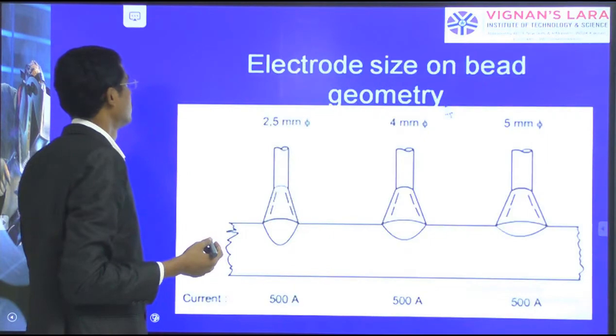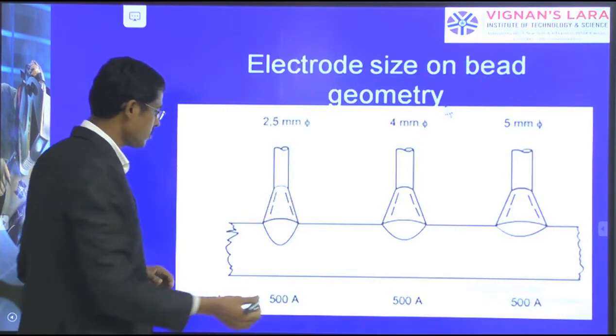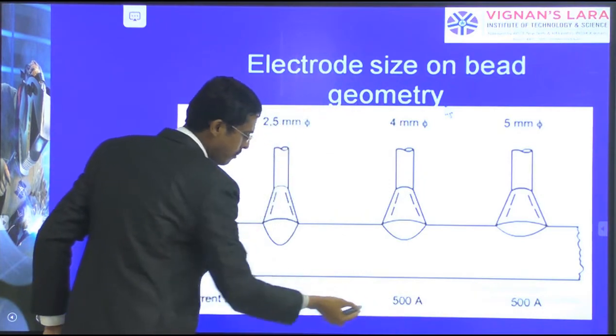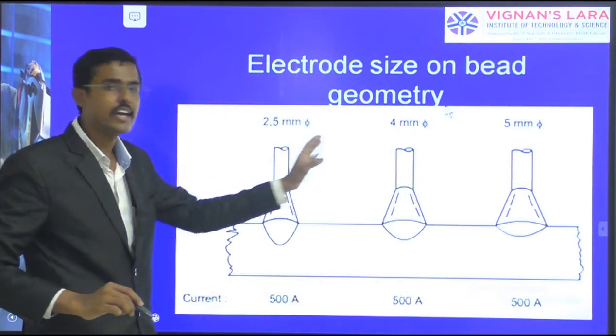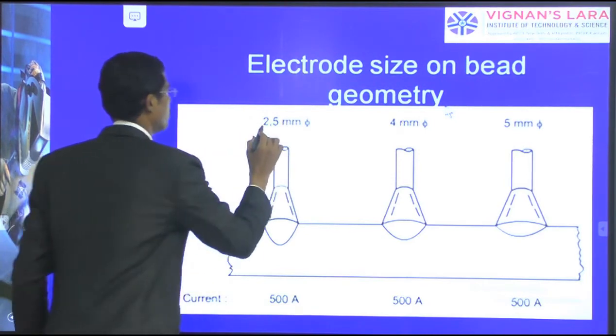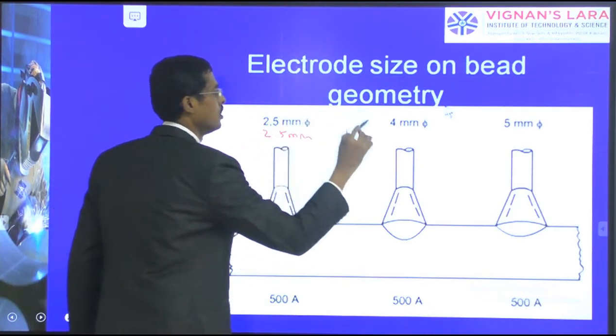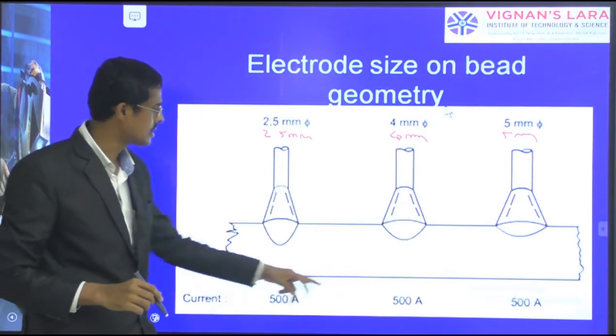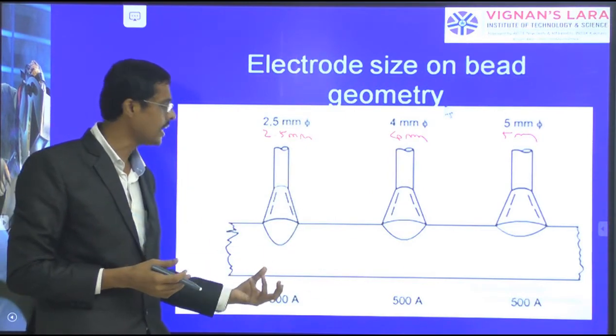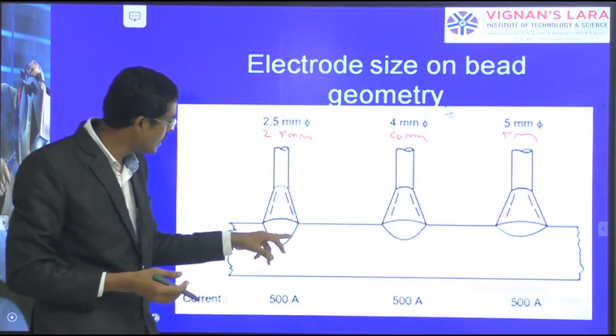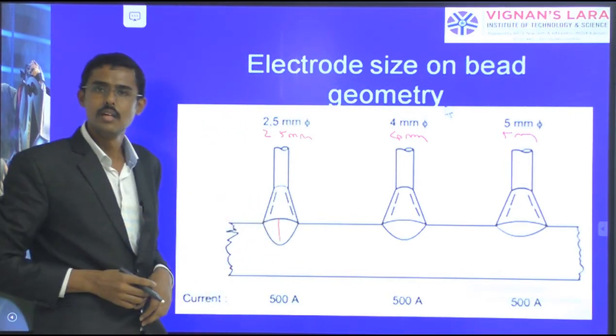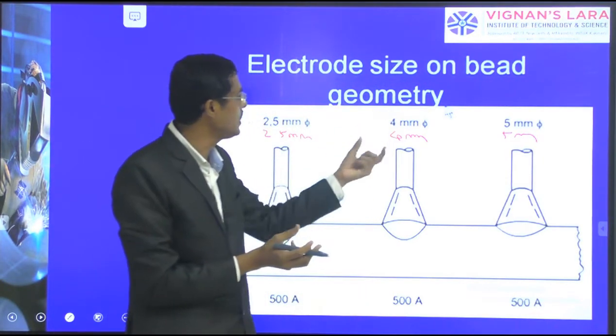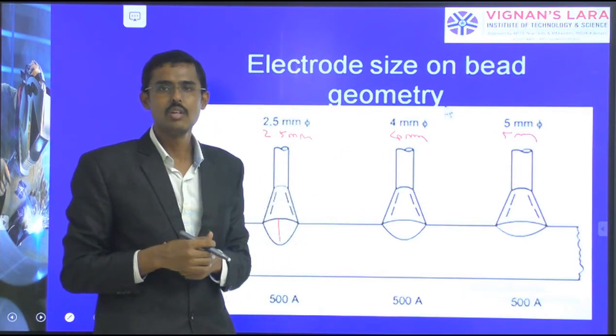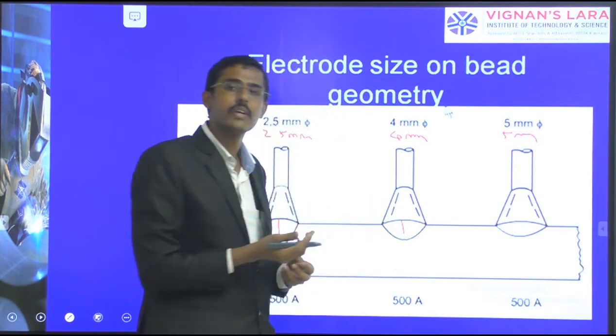So electrode sizes, we see I have taken 500 amp, here also 500 amp, here also 500 amp. But I have taken the variation of 2.5 mm, 4 mm and 5 mm. The thickness increases, but the current is the same. In such a case, what happens? With the same current supplied for a small diameter, proper welding occurs and proper penetration is formed. But now the same current is applied for the increased thickness. It is not sufficient to melt the required diameter. Therefore, the depth of penetration decreases.